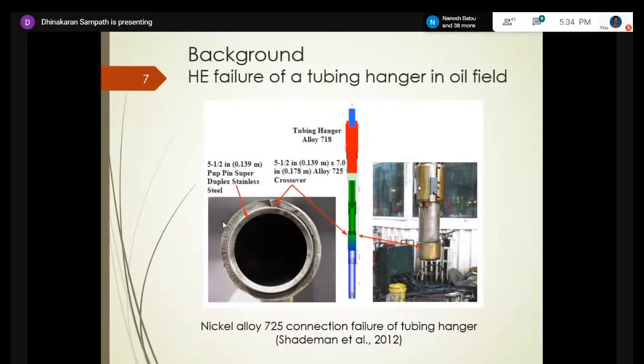That means the crack grows through the grain boundaries of the microstructure. They did several additional tests and found that it is only because of hydrogen from electroplating this section of the component, and also the hydrogen generated from the fluids that it was handling. So this is very critical. This is very expensive. As I told, they can't abandon the well and drill very next to it. They have to sort this out. They pull this out to understand it this way. They no longer tolerate failures like this.